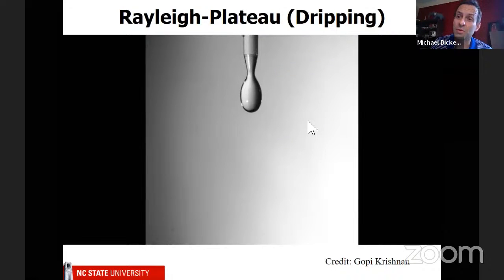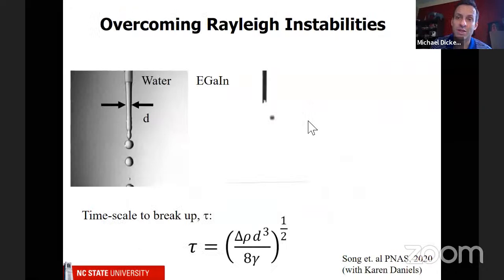Now, you could try to make something other than droplets by increasing the flow rate, but the stream will still break up, and it's called a Rayleigh-Plateau instability. So that same nozzle, if you increase the velocity, you can see that it will form a stream, and that stream, if you give it enough time, will break up into droplets because that minimizes the surface energy. So this is also driven by surface tension. So the time that is required for the stream to break up is proportional to the diameter, labeled here D, to the three-halves power.